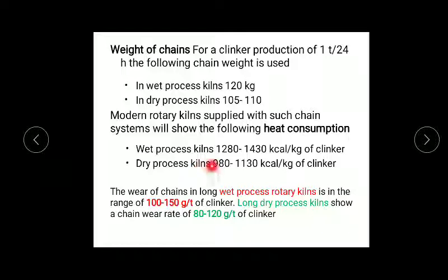means how much is the weight loss per ton of cement production. The wear of chain in long wet process rotary kiln is in the range of 100 to 150 grams per ton. ओके तो 100 to 150 ग्राम्स चेन का वेट लूज होता है पर टन ऑफ क्लिंकर, तो इतना वेयर हो रहा है. For long dry process kiln shows a chain wear rate of 80 to 120 ग्राम पर टन ऑफ क्लिंकर. So this is the wearing rate of the chain. Okay.